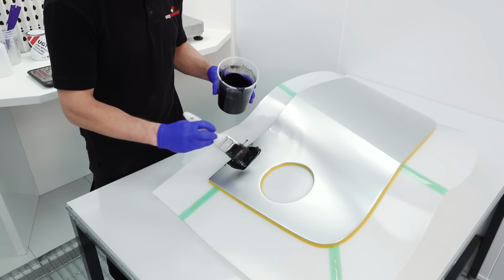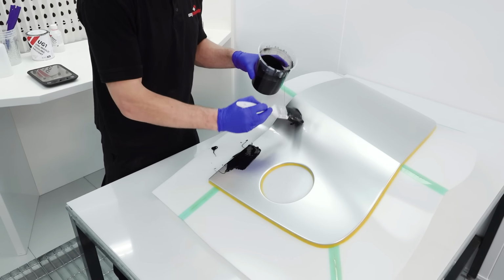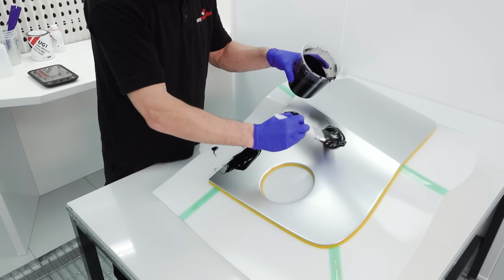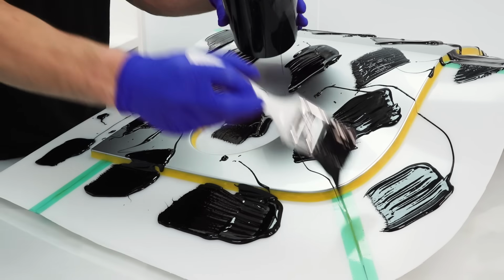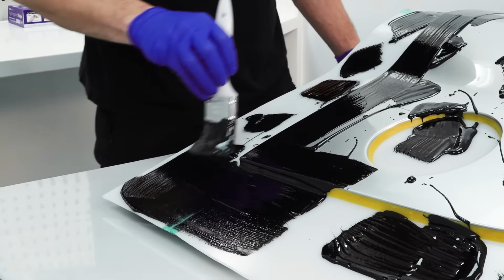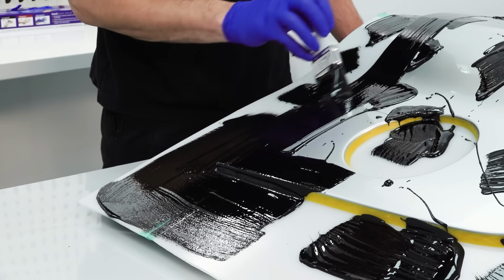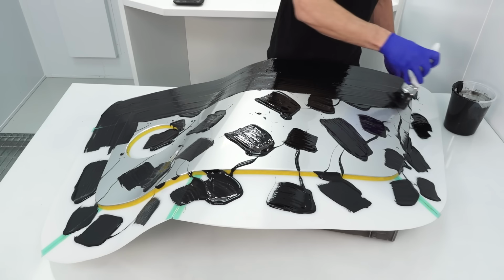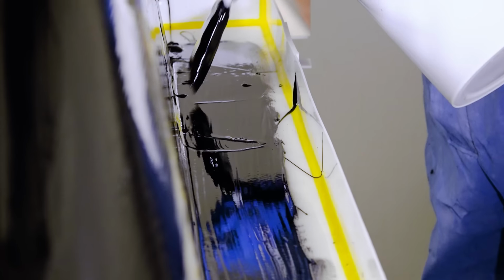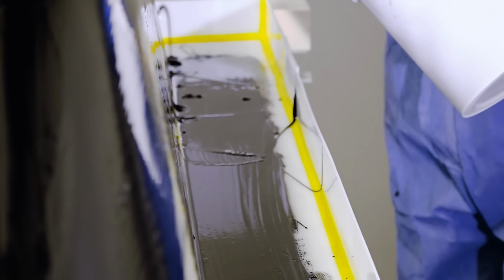Once thoroughly mixed, the gel should then be brushed evenly over the entire surface. To ensure an even coverage, I like to dot the entire mix at regular intervals over the pattern and then brush it out from here. When doing this, pay particular attention around the bottom of vertical surfaces, as this is where the gel can pool.